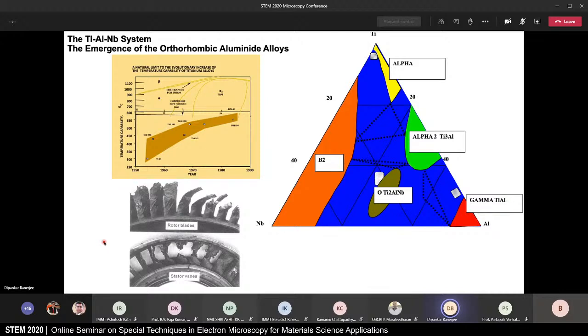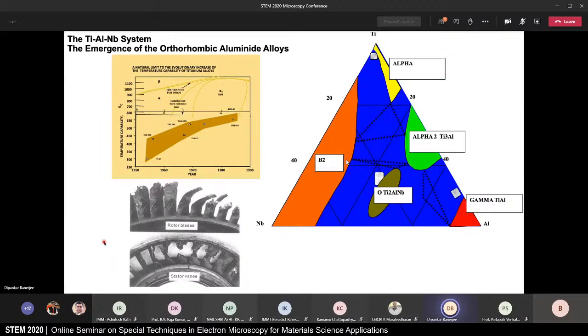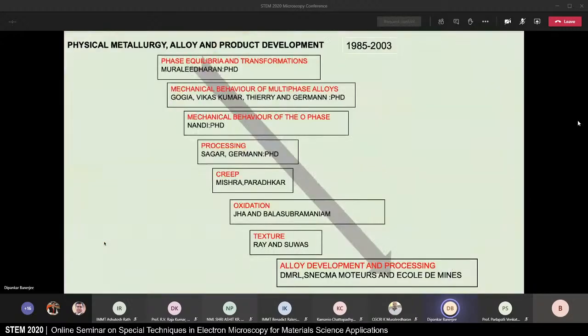The upper limit of this capability is defined by the oxidation resistance and the burn resistance of titanium alloys. And if you want to increase temperature capability, you have to look at the intermetallics in the titanium alloy system. So there's Ti3Al, there's TiAl, and there's Ti2AlNb, as shown in this phase diagram. And work at the Defense Metallurgical Research Laboratory focused primarily on the intermetallic Ti2AlNb.